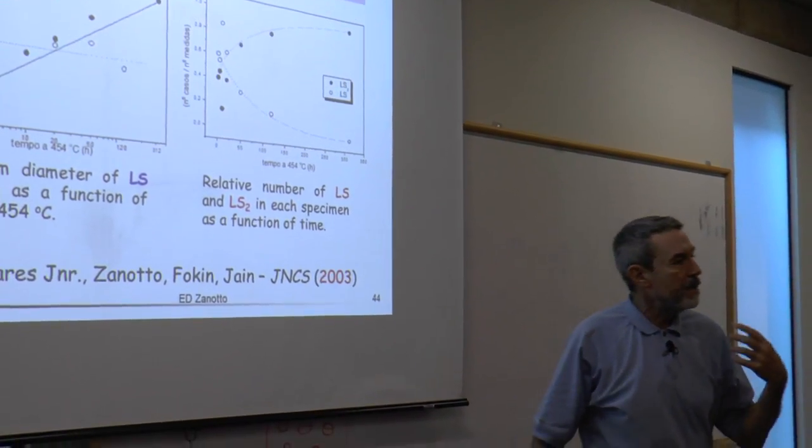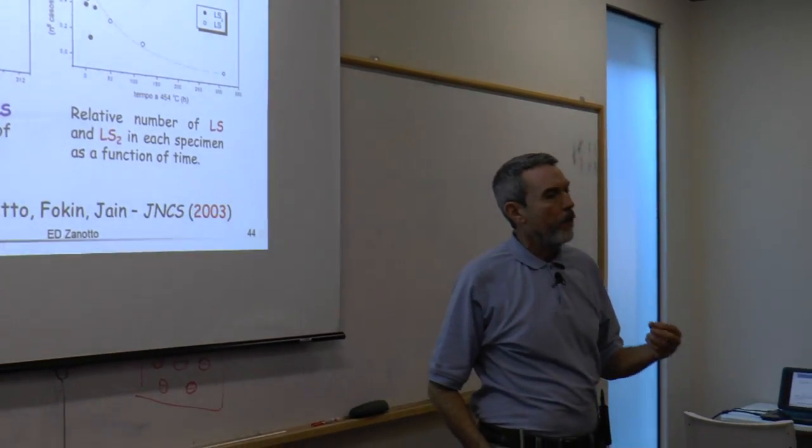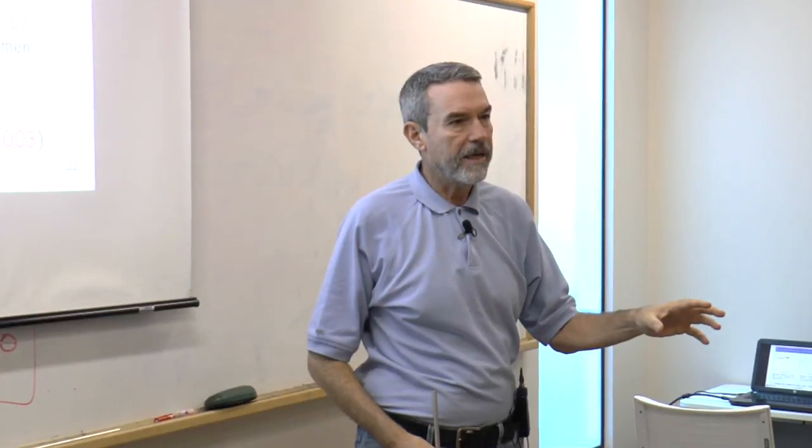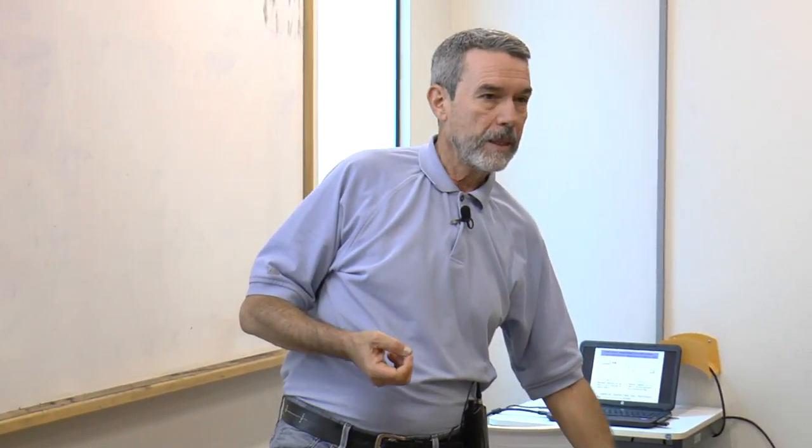But it does so simultaneously with the stable phase disilicate, which has the same composition as the parent glass. So there is a formation of a metastable phase in this particular system, but it does not affect the kinetics of the stable phase.